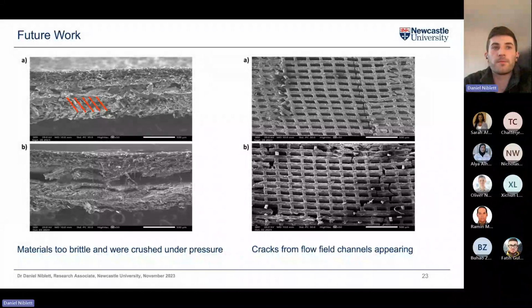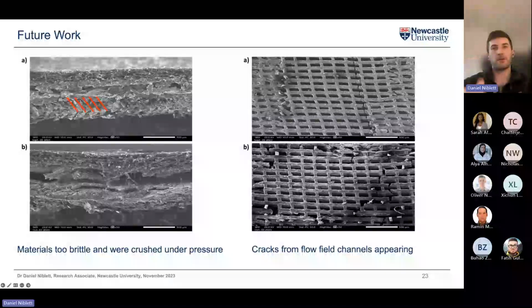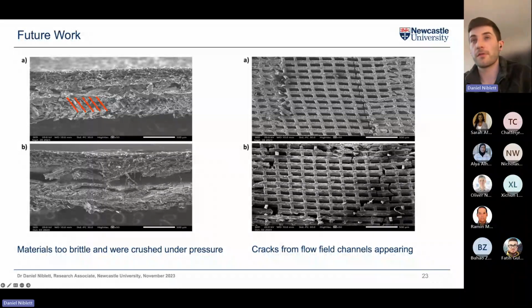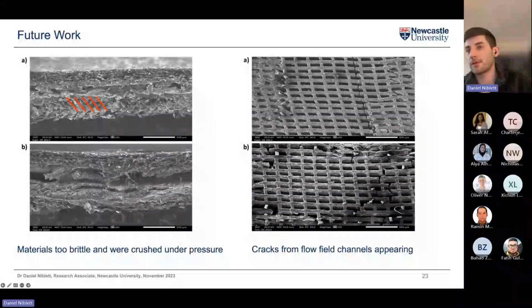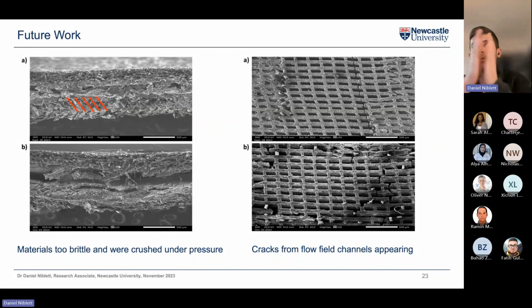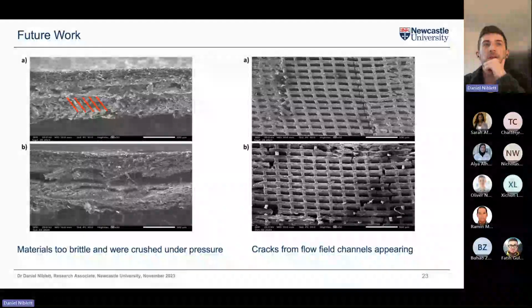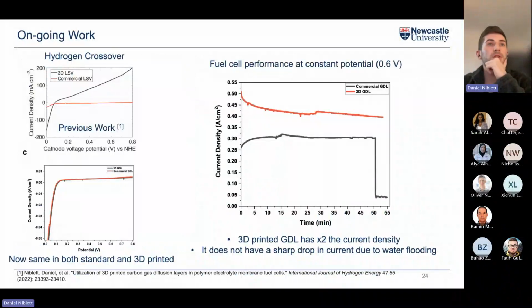the materials are quite brittle. The initial ones I showed with the defects with the walls, I've highlighted here in red lines. When the cell was compressed, you can see that the walls have collapsed onto each other in a diagonal kind of arrangement, and that's obviously something we don't want to happen. We want to preserve the structure, and you can see actually the cracks from the flow field appearing on the images on the right here, and that's where the compression has essentially cracked these materials. But we have improved that, so using a new type of resin, which is a different photopolymer, we've actually improved that now, and we don't get those effects.